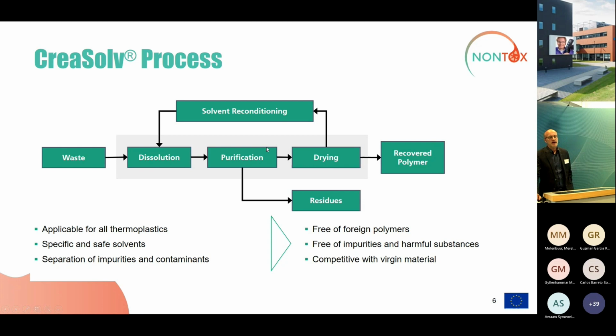Finally, after purification and separation of these residues, we had a drying step. Here the solvent is recovered and reconditioned to be reused in the process. And finally, we got a recovered polymer. Such a process is applicable to all thermoplastics, so we could use it for ABS, for PS, and for PC ABS. And we use specific solvents. So, of course, there's a specific solvent for ABS, another one for PS, and also another one for PC ABS.